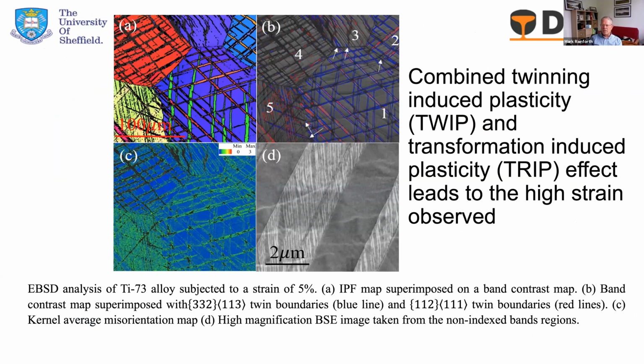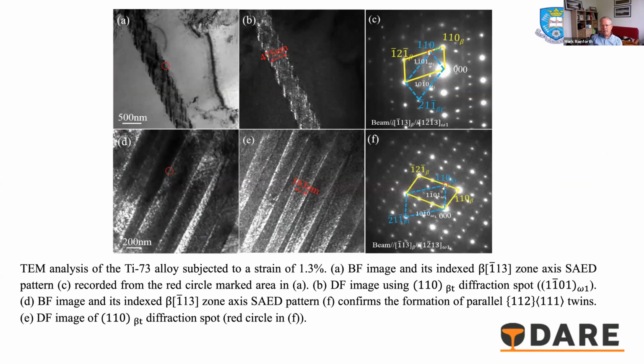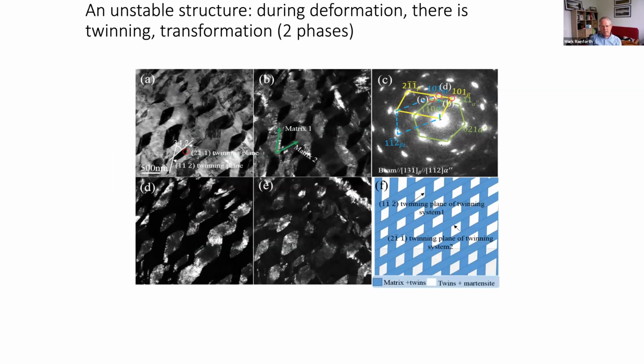We're using this twinning-induced plasticity, beg your pardon, transformation-induced plasticity and twinning-induced plasticity together. So if we get both of those mechanisms taking place, then we can generate these very high strengths. And I just can't resist showing some nice images of those two mechanisms taking place. And you get these very beautiful microstructures.